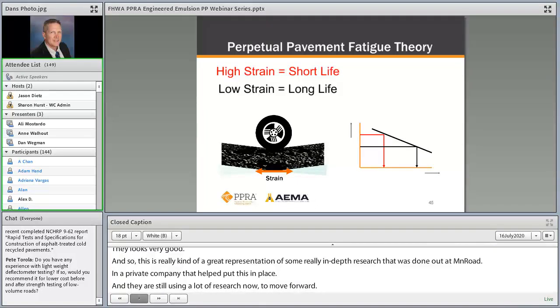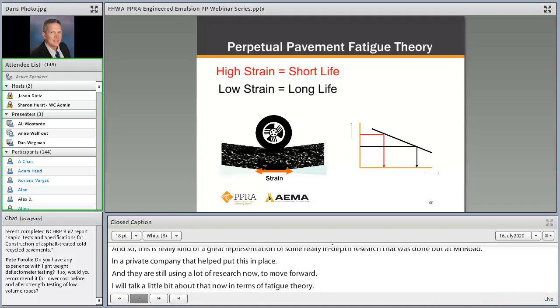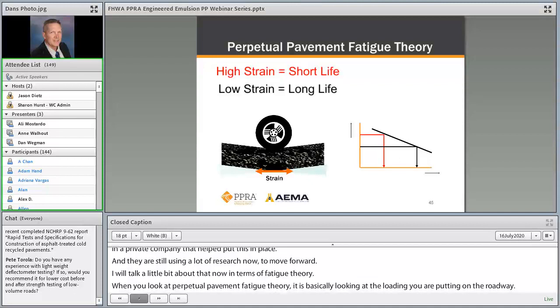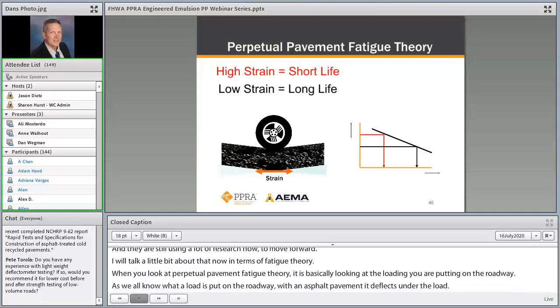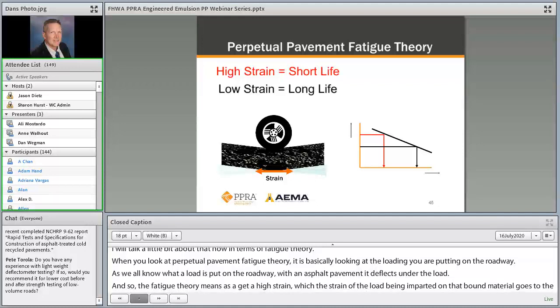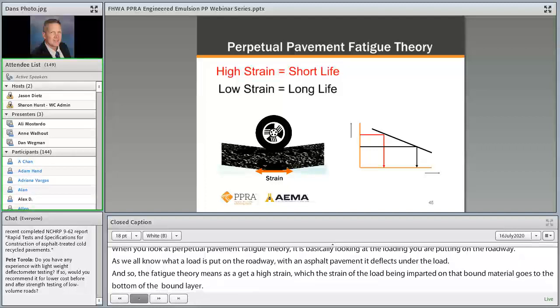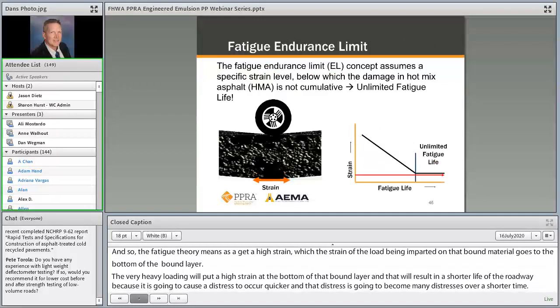When you look at perpetual pavement fatigue theory, it's basically looking at the loading that you're putting on the roadway. And as we all know, when a load is put on the roadway with an asphalt pavement, it deflects under that loading. So the fatigue theory means that if you get a high strain, which the strain of the load being imparted on that bound material always goes to the bottom of the bound layer, a very heavy loading is going to put a high strain at the bottom of that bound layer, and that's going to result in a shorter life of that roadway because it's going to cause a distress to occur quicker, and that distress is going to become many distresses over a shorter period of time. So the idea that you have a lower strain, you get a longer life, is the fundamental fatigue theory behind the perpetual pavement.